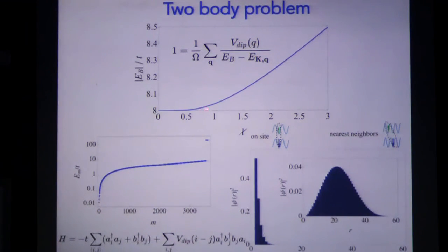When you solve the two-body problem, what you can see is that for values of chi lower than 0.5, you can have scattered states, and for values of chi above 0.5, what you have is bound states. That is, for all of these values of chi, you have just bound states. But remember that superconductivity is composed of non-bound molecules, scattered molecules, in order to form the Cooper pairs, in this case.